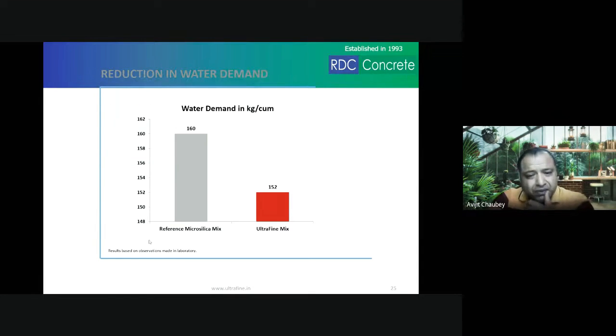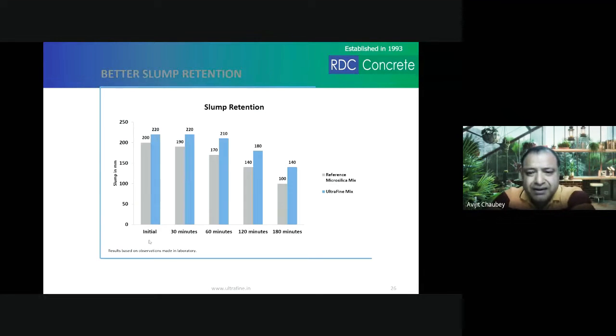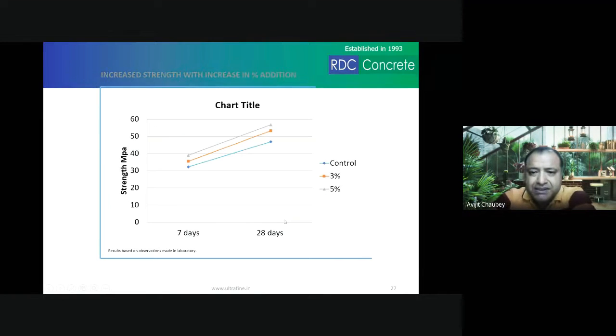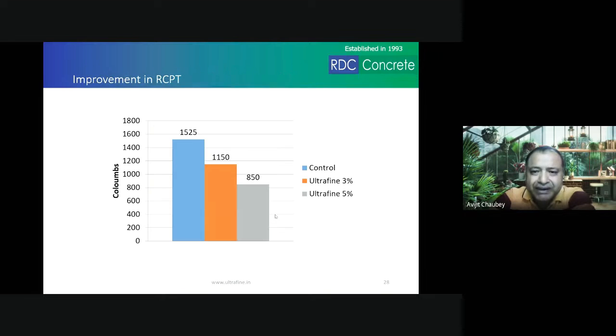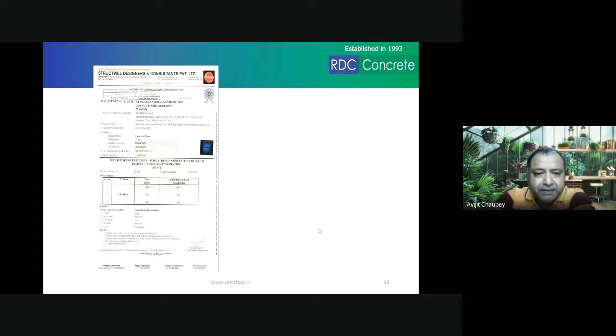If you see, these are some of the reference microsilica mix and ultrafine mix. This is the retention. You get much better retention in the ultrafine mix. The blue one is the ultrafine. The gray one is the microsilica mix. This is the strength with respect to the control. These are the actual strengths at 7 and 28 days. This is the RCPT test. Now, not just RCMT, even in the RCPT test, you get much better performance when you incorporate ultrafine.